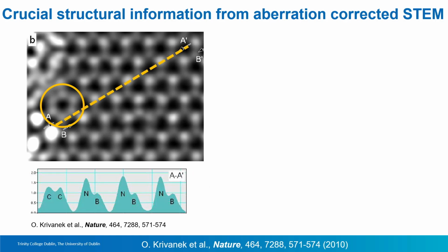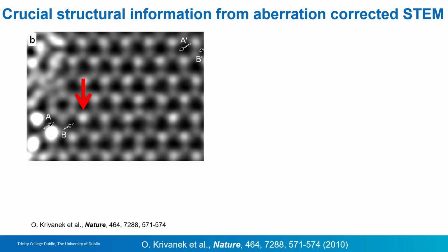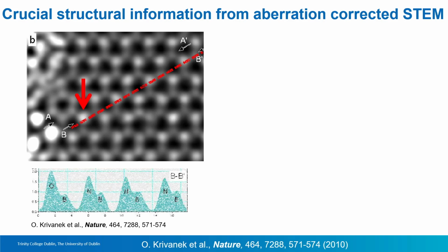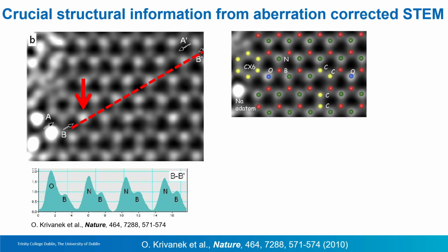If you do an intensity profile, you realize that here is a boron, a nitrogen, and then you can fit, and this corresponds to carbon atoms. A full ring of boron nitride was replaced with carbon atoms, probably coming from the solvent we had used, NMP. You can also see that there are much brighter atoms, brighter than nitrogen. Again, you can do the same thing, and that corresponds to an oxygen. So from one single image, you can analyze, atom by atom with atomic resolution, the types of atoms and substitutions that you have.